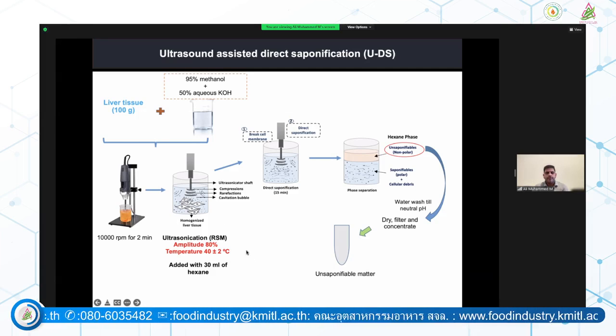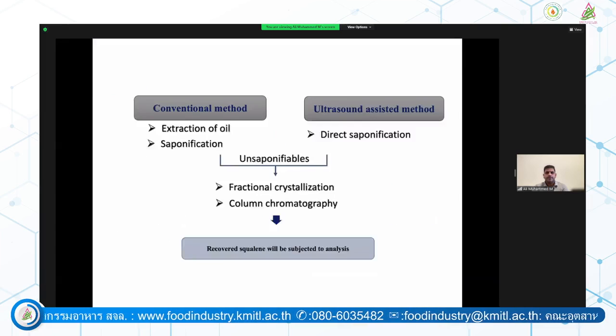With ultrasonication, we found that the temperature could be reduced from 70 degrees to 40 degrees, and the extraction could reach the maximum, because we also add potassium hydroxide. In addition to the reaction, the potassium hydroxide also facilitated the breakdown of cells for maximum yield compared to the conventional method. After the reaction, the upper, nonpolar phase was collected with hexane, and this unsaponifiable fraction was collected. So with just one step of ultrasonication, we can avoid so many steps of extraction.